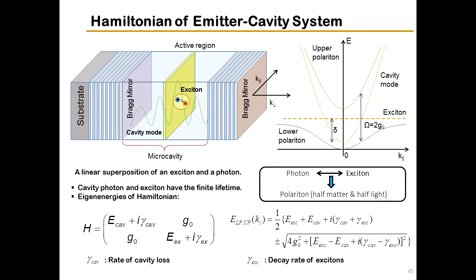If you excite the system very hard, this quasi-particle picture will disappear as you increase the excitation and cause a saturation, when the detuning due to the polariton-phonon interaction exceeds the Rabi oscillation frequency. Then these polaritons are lost, and you get back to the exciton and the cavity photon. The cavity photons and excitons couple because the excitons are normally formed and decay by an interband transition. Now, the eigenenergies are given by these equations, and this is the Hamiltonian of the system.